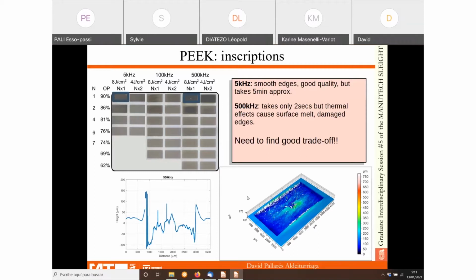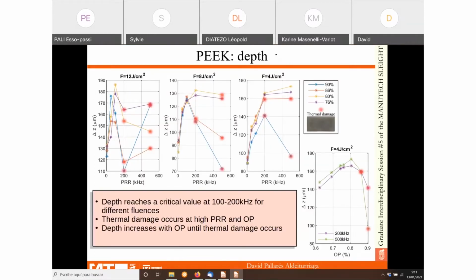Okay. And maybe we can get some idea taking a look at the depth data. Here we see a clear tendency to increase depth with repetition rate and overlap. But when we reach a critical value of 100 to 200 kilohertz, depending on fluence, these thermal effects start to occur, and disturb the measurements, as can be clearly seen at higher fluence.